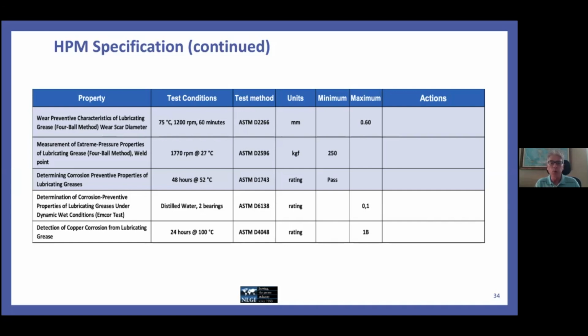If you recall back to Mike's slide where he showed an example of some of the tests that we were discussing, we eventually made a shift in our proposed limits. This is one where we started with 200 kilogram minimum weld load as a starting point. After interviews and discussions with the steering committee, we said that is just not really challenging. That doesn't mean very much in terms of extreme pressure capability. So we decided to move it to 250 kilogram, which was met with pretty round agreement from the working committee, working group, steering committee and interviewees.